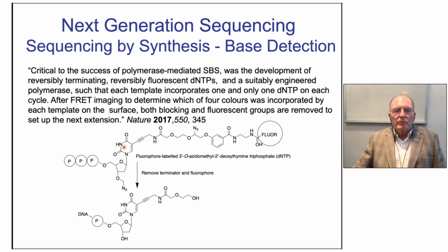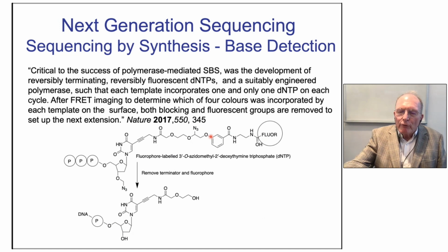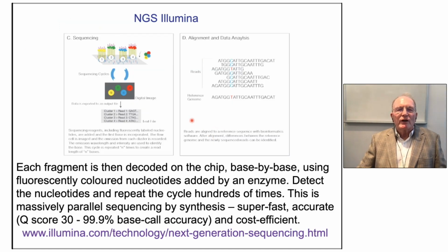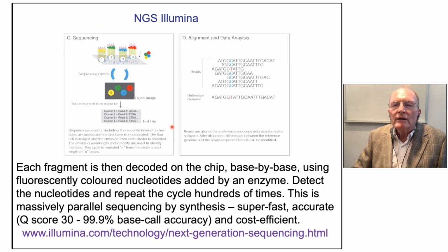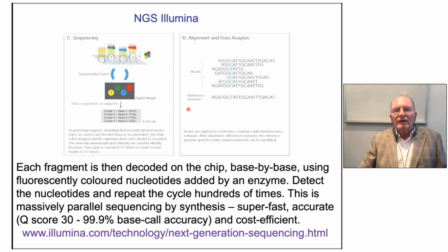They can image it, and this will be the complementary base to the chain that's being grown, added as it's growing. And then by simple reduction of these azide groups, in each case, this azide and this azide, the free OH in the 3' position and the fluorescent probe are removed. So it's added by growth, detected, and then taken off, so the next building base can be added on sequentially. And this is done on a chip, base by base, on a massively parallel scale, using fluorescently colored nucleotides, which are added by a DNA polymerase enzyme. And then the alignment is carried out against the reference genome so that they can read the sequence.